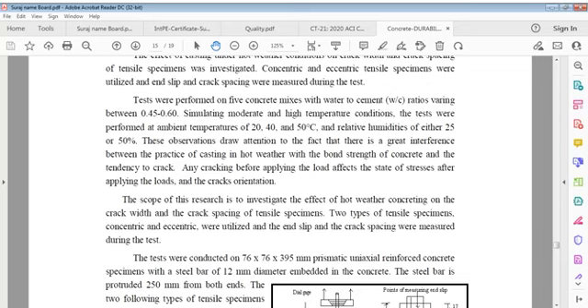These observations draw attention to the fact that there is a great interference between the practice of casting in hot weather and the bond strength of concrete and tendency to crack. Cracking before applying load affects the state of stress after applying loads in crack orientation. The scope of this research work is to investigate the effect of hot weather concreting on crack width and crack spacing of tensile specimens. Two types of tensile specimens, concentric and eccentric, were utilized, and slip and crack spacing were measured.